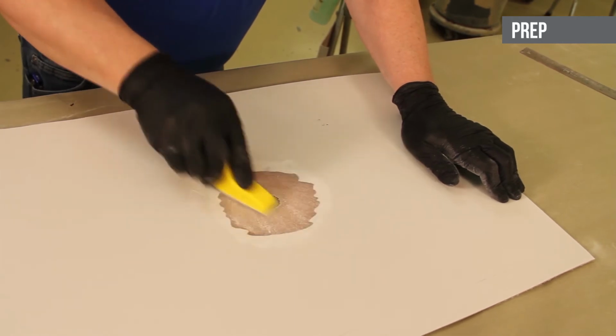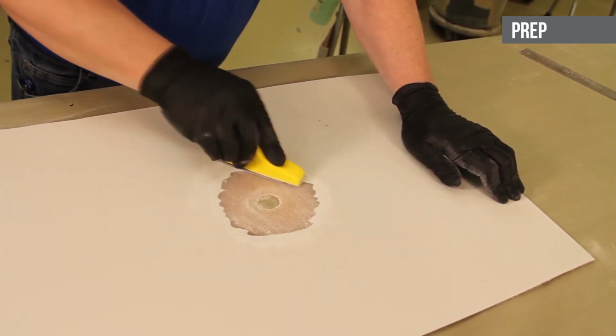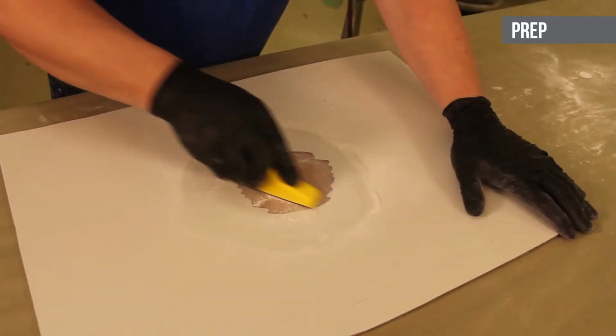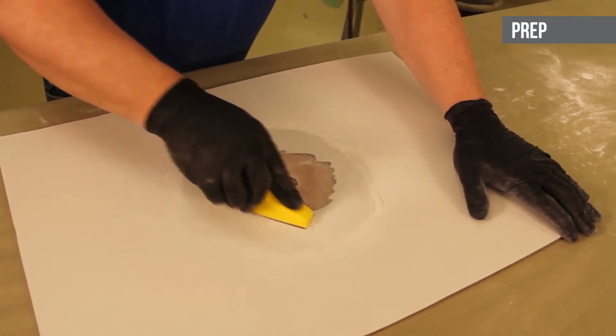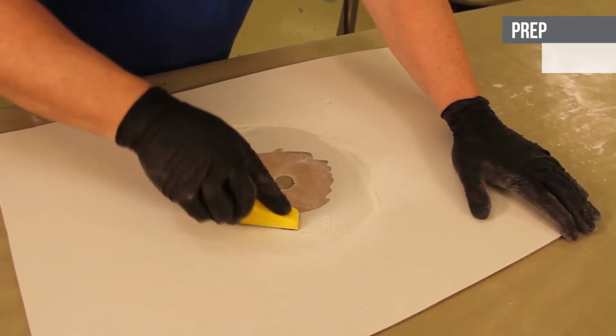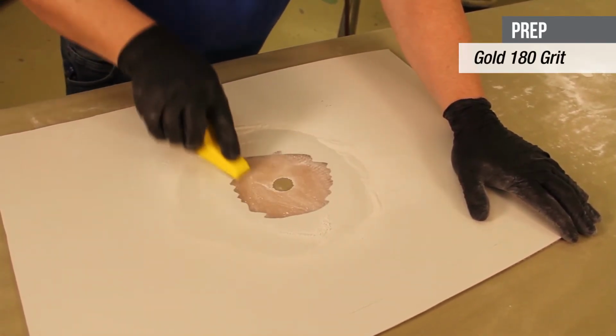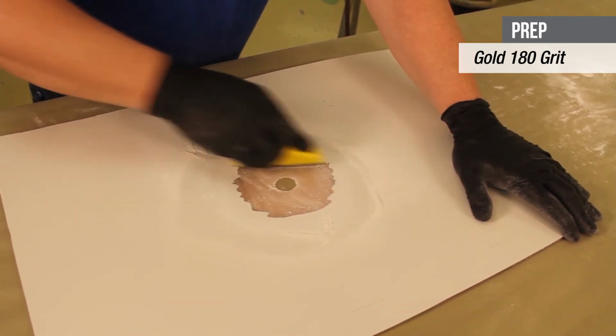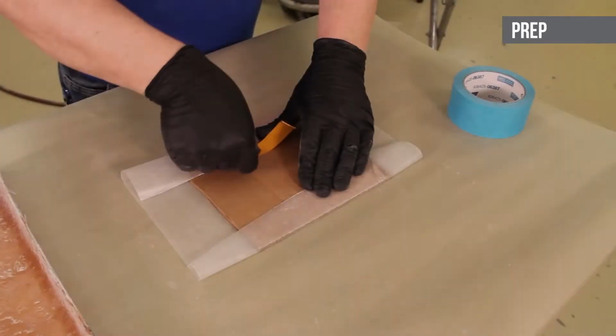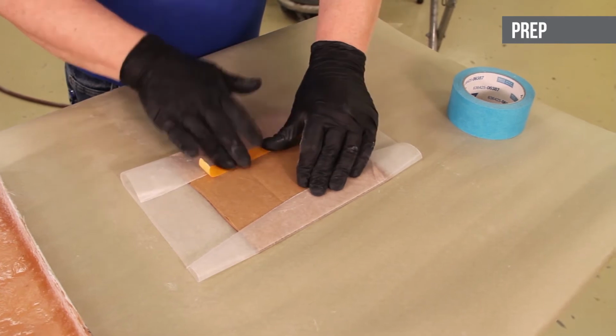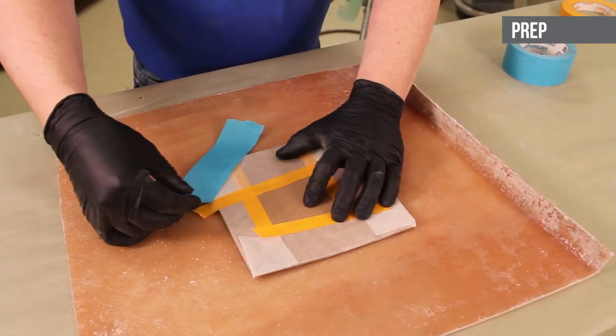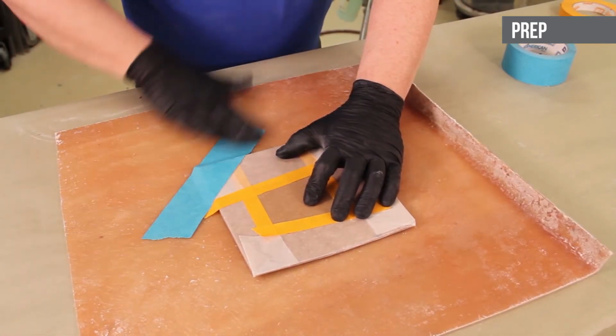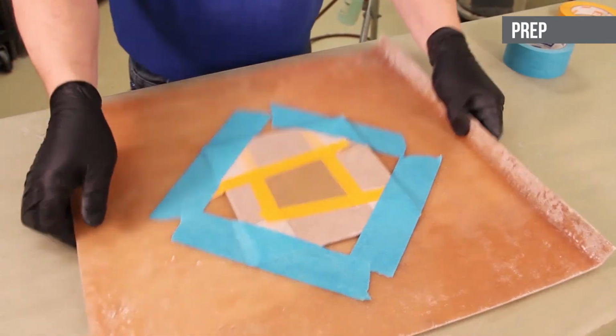Sand several inches beyond the repair area and taper the edge of the hole. Feather edge or blend the sanded area into the finished area with the gold 180 grit sandpaper. Tape a piece of cardboard covered with wax paper to the backside of the hole if needed. This will make applying the resin and mat easier.